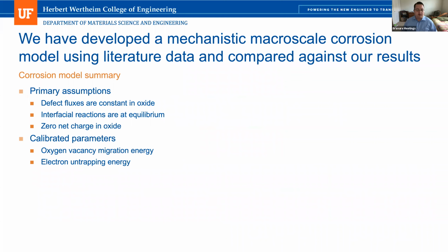And the most important part of the STAC tool will be a corrosion model at the macro scale. So we're working on developing that corrosion model as well. But this is a macro scale model, so we need to make assumptions. So first off, we're just going to have a single representative oxide. We also need to have other assumptions. So we're assuming defect fluxes are constant in the oxide. We're assuming the interfacial reactions are at equilibrium and a zero net charge in the oxide. So we have a charge compensation condition.